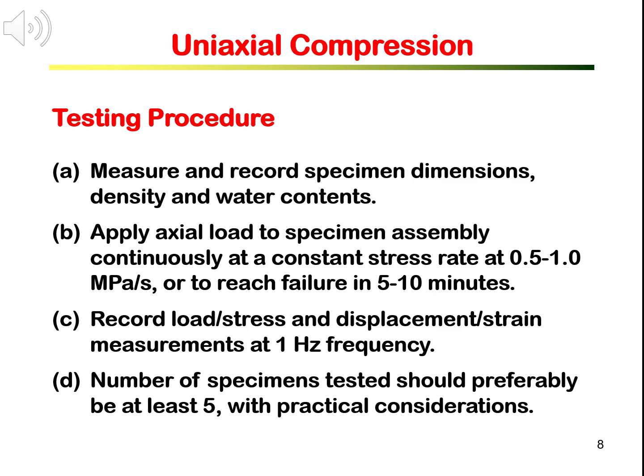Attach the axial and lateral strain gauge measurement devices to the specimen as we have learned on slide 5. Place the specimen assembly, as shown in slide 4, in the compression machine, centered with the axial loading piston. Then we can start applying axial load to the specimen assembly continuously at a constant stress rate of 0.5 to 1 megapascal per second, or to make sure it will reach failure in 5 to 10 minutes.